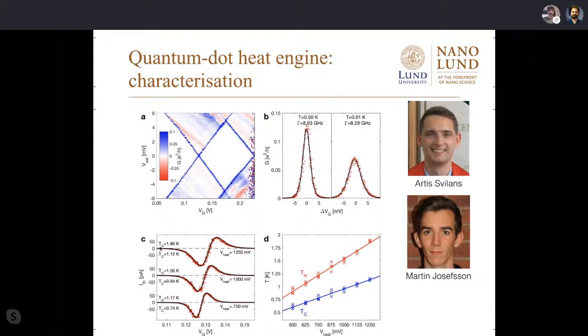So this is now applying a temperature difference between the hot side and the cold side, tuning with the gate voltage, tuning the Fermi energy past this resonance. And then you see this very characteristic sign change in the thermoelectric current that is produced, because either you have the Fermi energy below the resonance or above the resonance, and then you get either hole or electron transport, or electrons to the left or to the right, depending on how you choose to see it.